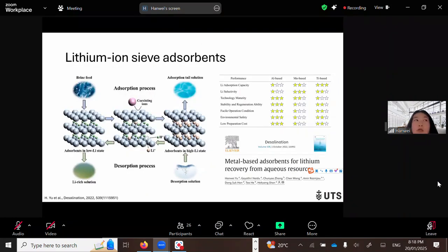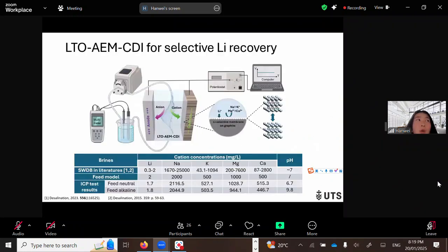And now this is our third strategy based on the lithium ion sieve adsorbents. Lithium ion adsorbents, including LMO and LTO, have the memory effect, that is, they have some specific sites for lithium. After activation, these sites are empty, exchanged with hydrogen, and during the absorption process, the lithium ions prefer to occupy these old sites first, so that it increases lithium selectivity dramatically. And in this research, we use the LTO-AEM-CDI for selective lithium recovery.